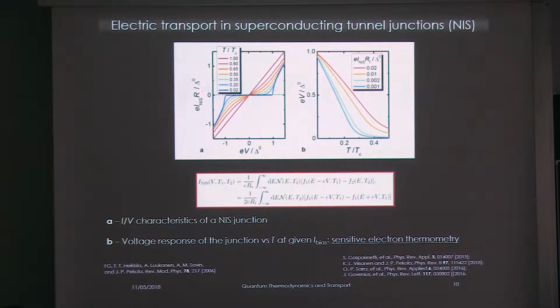If we take the very basic normal metal-insulator-superconductor junction, here is shown the electric current versus voltage at different temperatures. You see that at low temperature there is a gap. There is a strong current suppression in the presence of the superconducting gap, and then by increasing the temperature we increase the number of quasi-particles, and so we smoothen the curves. How is it operated typically?